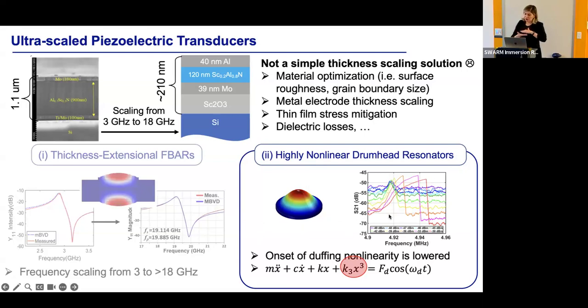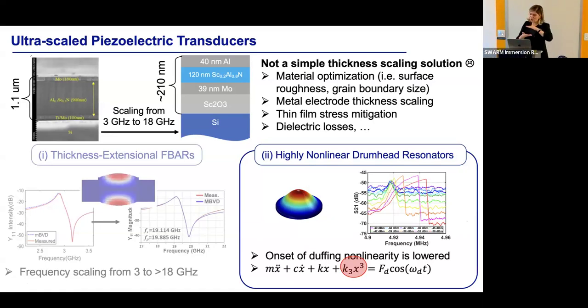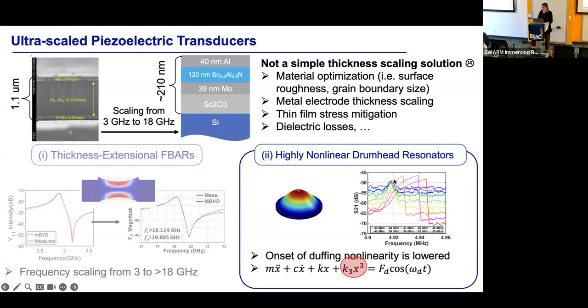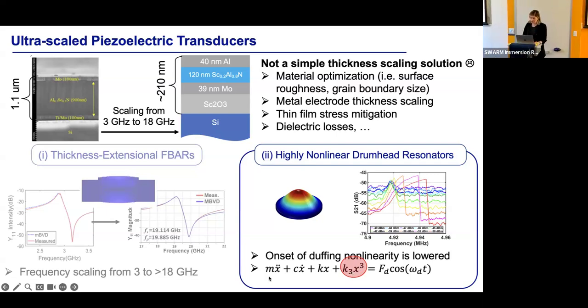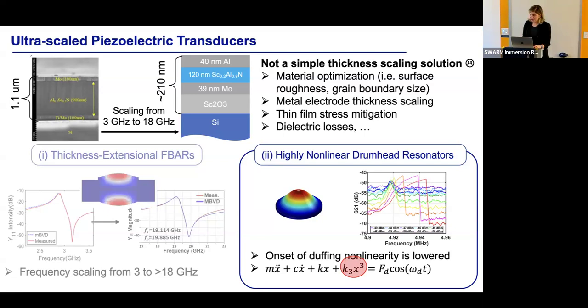And when the thicknesses become thinner and thinner, there is what we call Duffing nonlinearity that increases, which shows us a bifurcation in the frequency response. What this means is that the geometrical nonlinearities kick in at lower input power levels as your transducer becomes thinner and thinner. And you can see these non-symmetrical resonance modes with bifurcated frequencies. Now, a lot of times you want to stay away from these nonlinearities. However, you can also embrace and leverage these nonlinearities that show up in your harmonic oscillator equation, and see how we can use these to build more interesting sensors, all right?